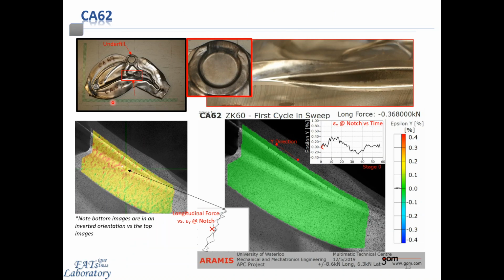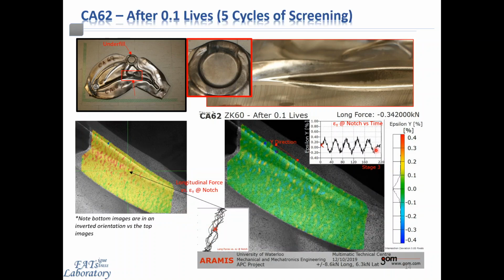Now, if we look at one loading cycle in more detail, we can observe the following. Firstly, in the animation on the right, we can see the evolution of the full field strain over the entire cycle. On the left, we can see a green crosshair in the critical region where strain is accumulating at peak tension. And on the graph on the right, we can see the evolution of the strain for that particular point over the duration of the cycle. It begins at 0 load and then 0 strain, and then progresses towards 0.4% strain at the peak tensile part of the loading, and then reverses into the negative strain and compression, and then returns back to 0.